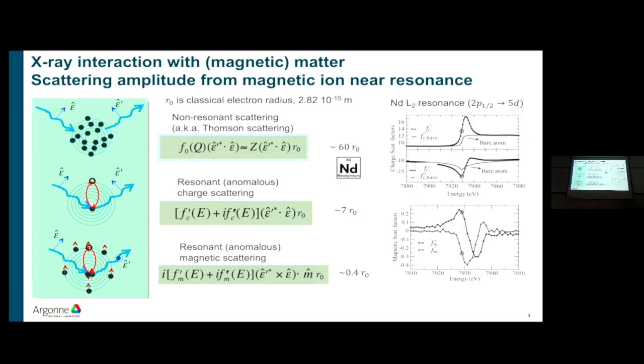Now, if you have spin in the valence electrons, so you have a magnetic atom, you're exciting an electron from a core level that also has a spin. So that spin of the core electron, when it's excited, interacts with the spin of the electrons in the valence orbital, or the outer orbitals, or the valence band. And you get sensitivity to the size and the direction of the moment. And again, this is a second order process. The electron comes back, fills the hole, and you get radiation out. And you see that the polarization now is different. Now it's sort of rotated, but this magnetic scattering amplitude captures the strength of this effect, and the direction of the magnetic moment in the atom, it's also in there.